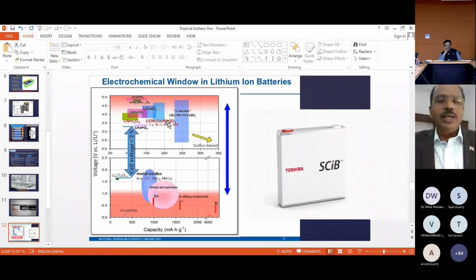But you can see the red regions on the top and bottom. On the anode side, you have the red region where a solid electrolyte layer is already formed. And even for cathodes, as you go to higher voltage, you start seeing some SEI, even on the cathode, which doesn't happen for the conventional materials.